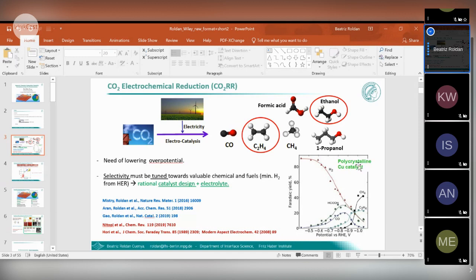When you're working with copper catalyst, just polycrystalline copper, if you change the potential, you see that the selectivity is changing. If you work at low overpotential, you get mainly hydrogen. And if you go to the relevant potential, you can get the hydrocarbons, but these potentials are relatively high. So there is a need of lowering the overpotential. And the beauty of this reaction is that if you change the catalyst structure and composition, and you also tune the electrolyte, you can modify the selectivity of your catalyst.